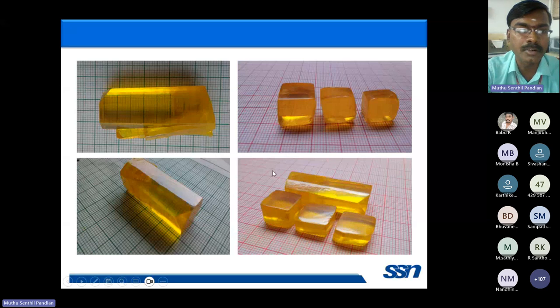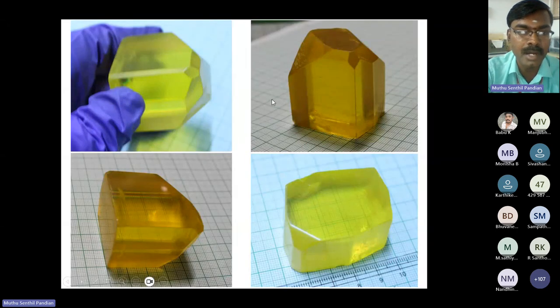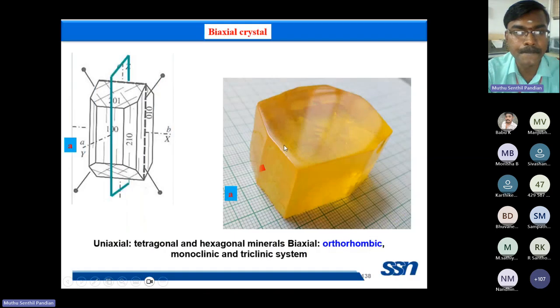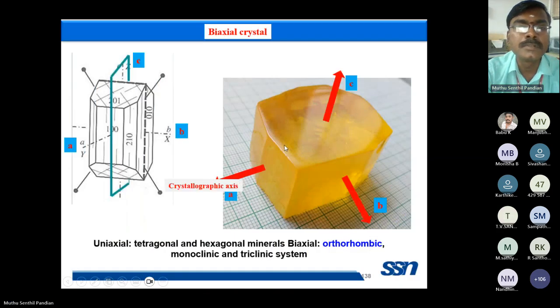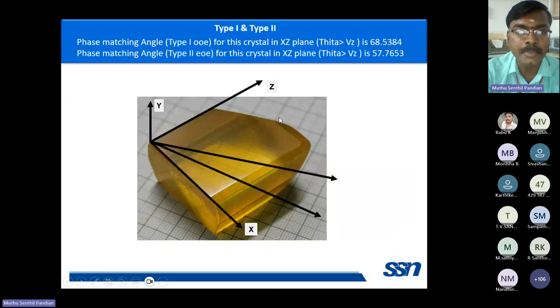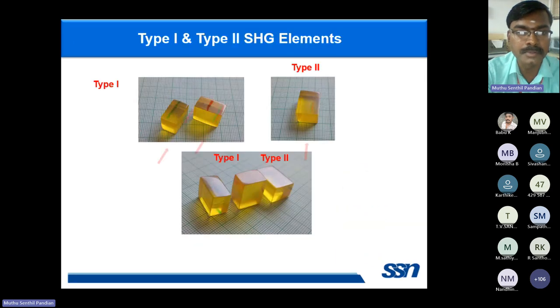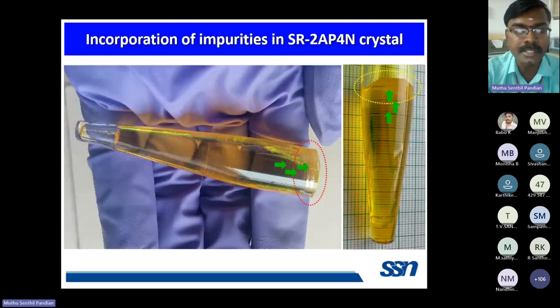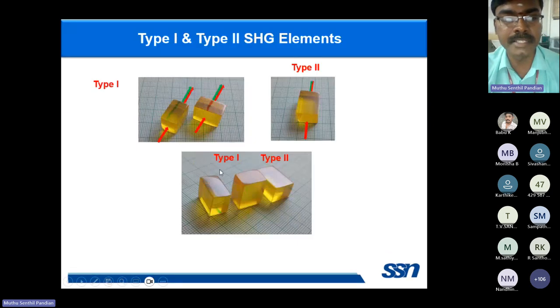This is the crystal grown by this point seed rotation technique. This much large size crystal is possible by this point seed rotation technique. So we have selected to harvest the type 1, type 2 SHG element, and we have successfully made it in the RRK lab. From this 4-nitrophenol derivative single crystal, we have successfully fabricated this element.